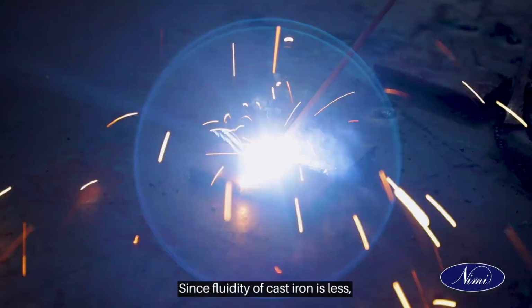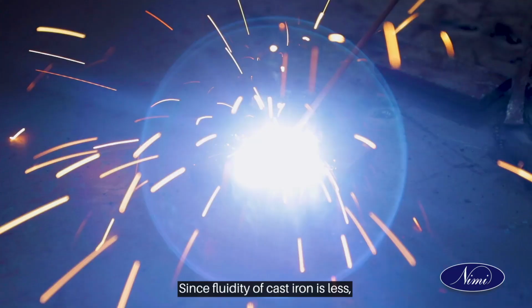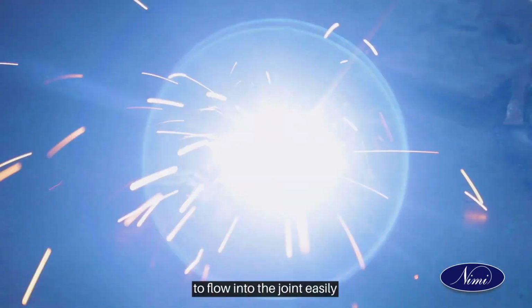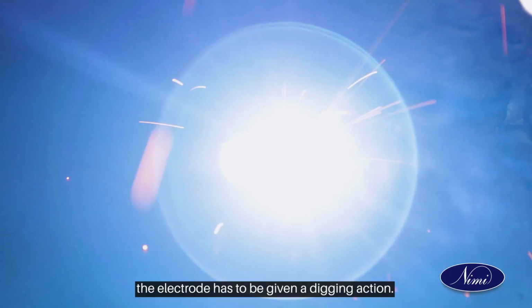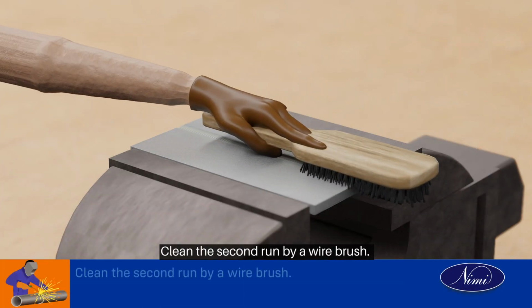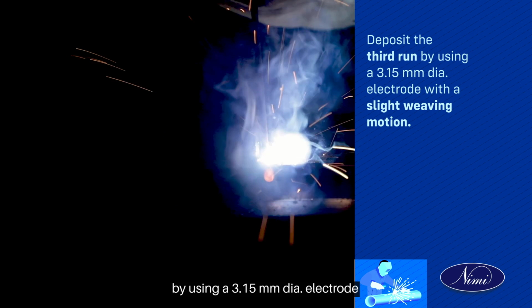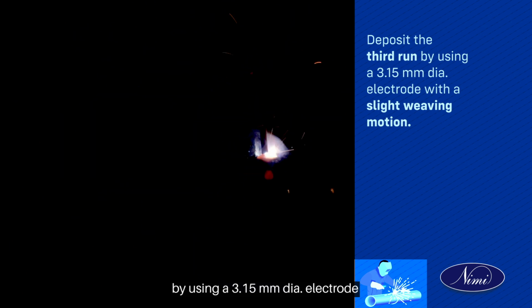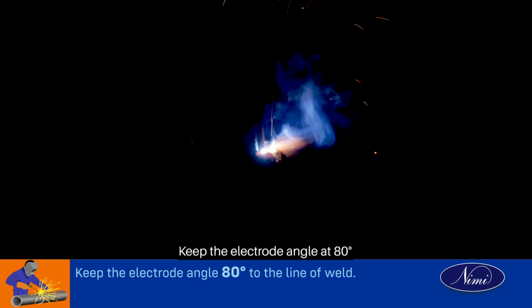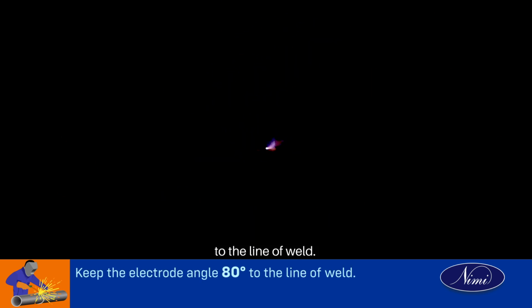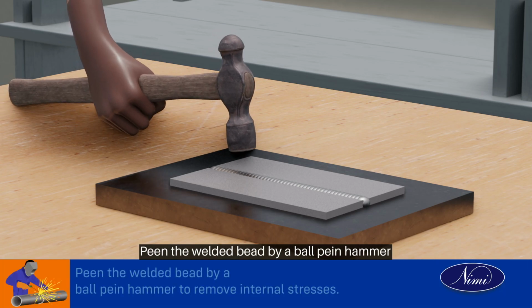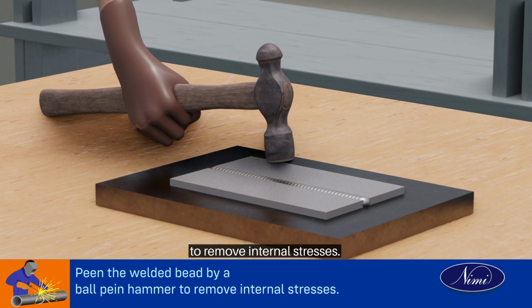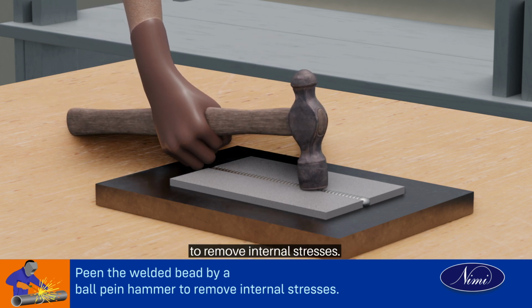Since fluidity of cast iron is less, to make the molten metal flow into the joint easily, the electrode has to be given a digging action. Clean the second run by a wire brush. Deposit the third run by using a 3.15 mm dia electrode with a slight weaving motion. Keep the electrode angle at 80 degrees to the line of weld. Peen the welded bead by a ball peen hammer to remove internal stresses.